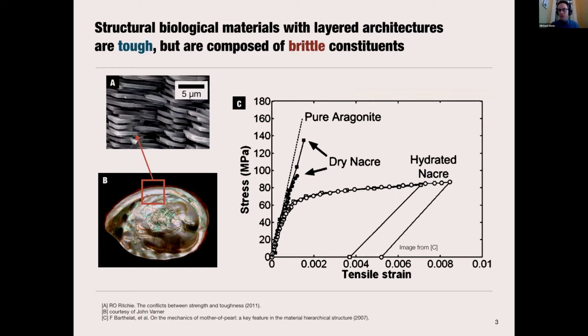And while there can be a huge discussion about the role of hydration in these materials, I really just want to focus on the hydrated case, because that's the native case, how the shell actually performs in its native environment. And you can see that the mechanical response of these materials is very, very different. The aragonite is typical of a ceramic. It's fairly linear in stress and strain up until catastrophic failure. Whereas the nacre has this almost elastoplastic response.